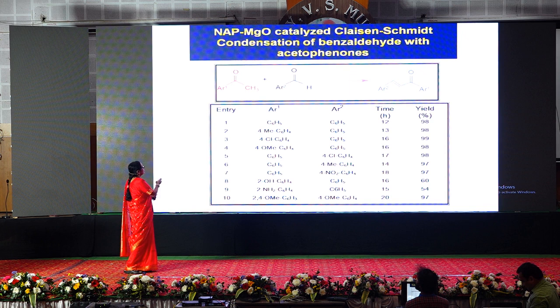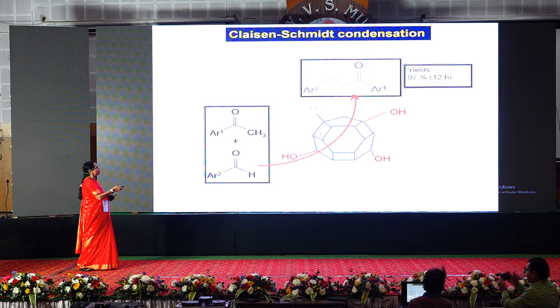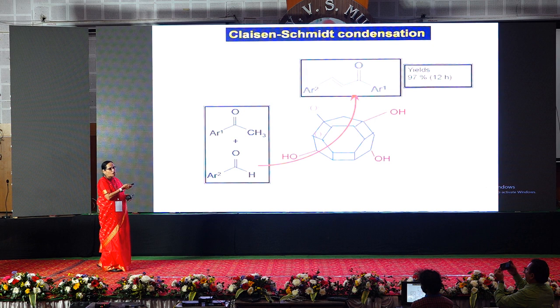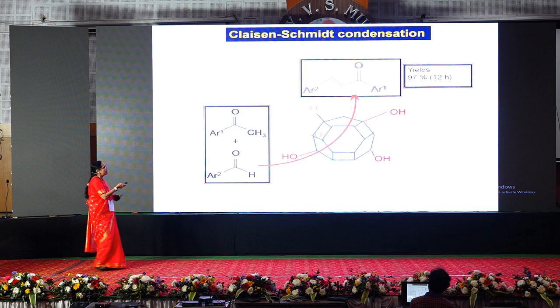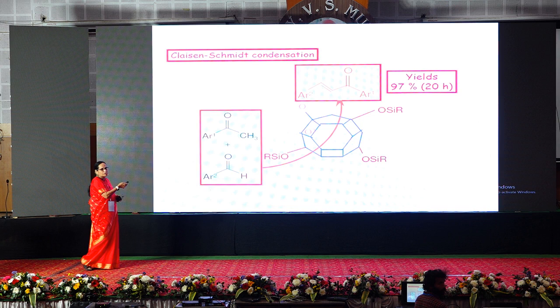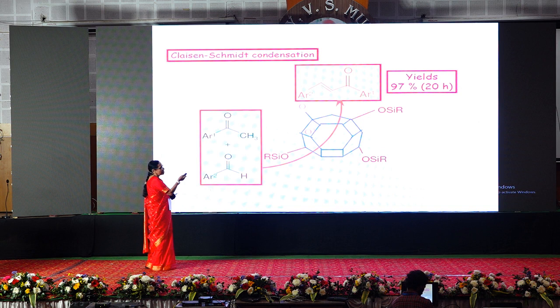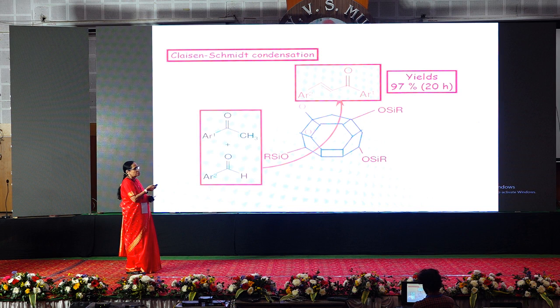And you can see this is the number of different aldehydes we took and different types of chalcones we made. And I told you, we don't know whether the OH is also good, or this other O2- is important. So what we did is, we did the reaction like this, 97% and 12 hours. Then we silylated the OH groups and did the reaction, and it takes 20 hours. That means the Lewis and the Brønsted basic sites both are important for this reaction.